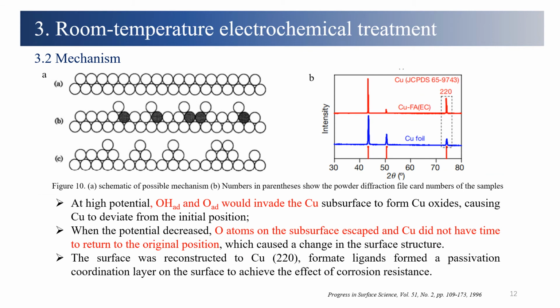After searching some papers, it can be explained as follows: at high potential these two adsorbers would invade the copper subsurface and cause the copper to deviate from the initial position. When the potential decreased, the oxygen atoms on the subsurface escaped and copper did not have time to return to the original position, so the surface structure was reconstructed to copper 220.